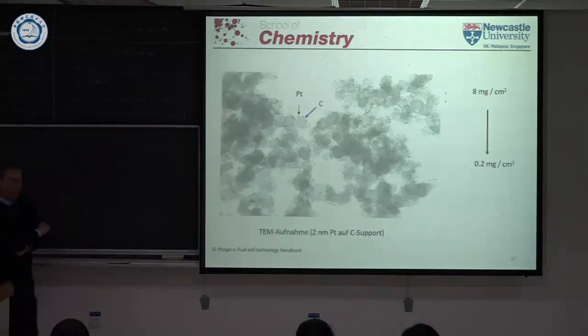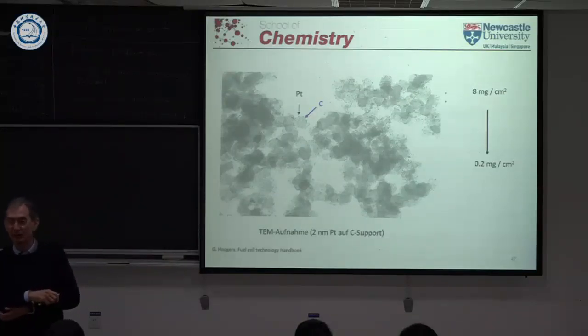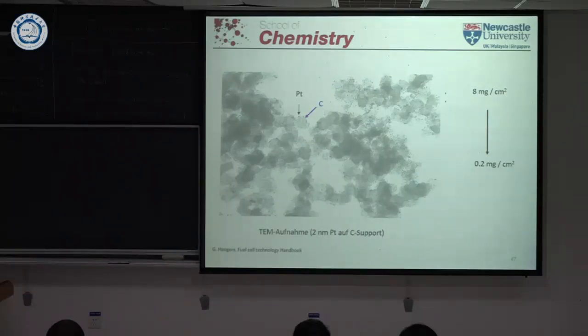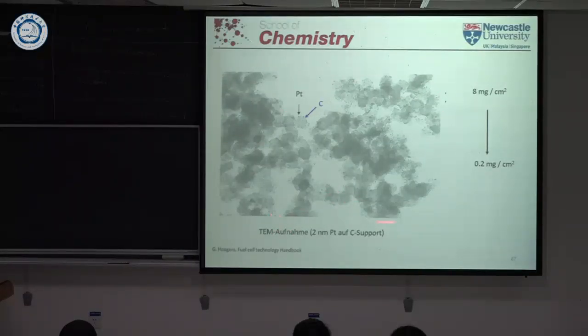Now this shows actually then more in a realistic way, looking at the transmission electron micrograph, how a catalyst layer sort of looks. These are the carbon particles here, these gray areas. You know, carbon is a material that has a lower Z, so it's not that strong contrast in the transmission electron micrograph. So you see this actually as gray area, while the platinum particles you see as really dark spots. Here it's a little darker because you have more particles on top of each other, so they are stacked, and that makes it here a little darker. But in principle, the small particles are the platinum particles and the larger ones are the carbon. And this is like a typical situation of a technical catalyst for 2 nanometer platinum particle on a carbon support.